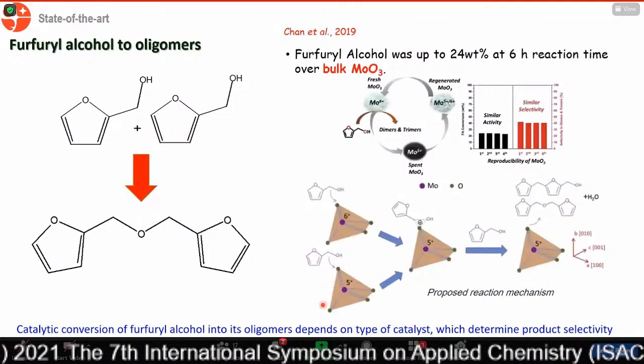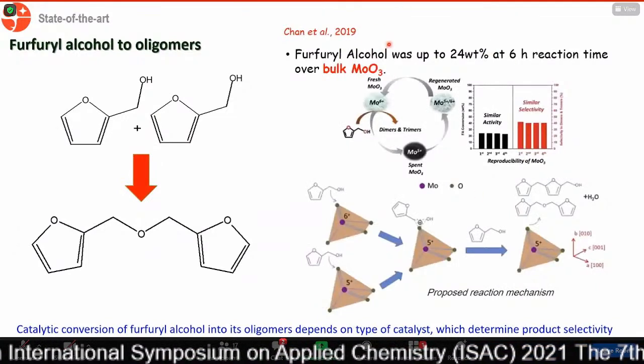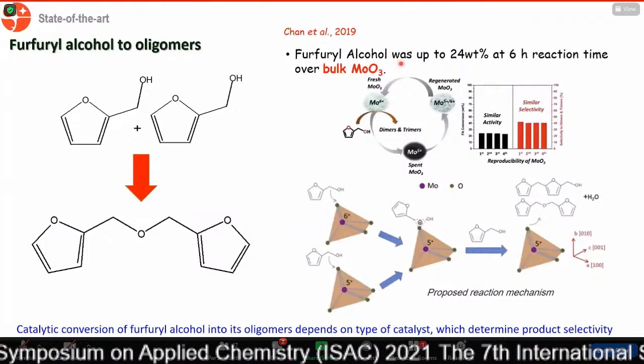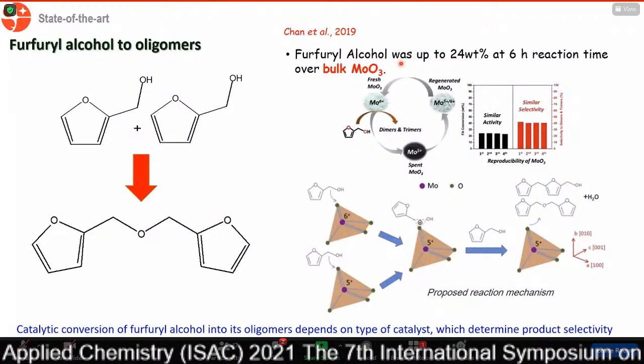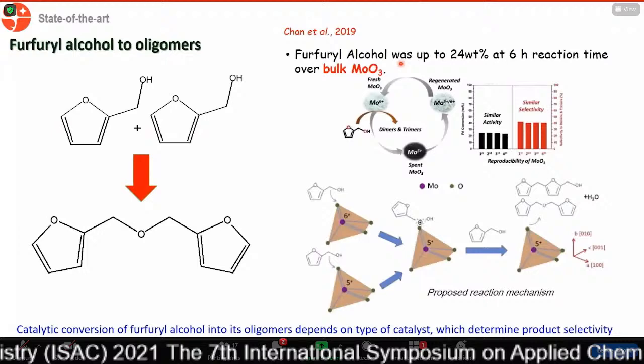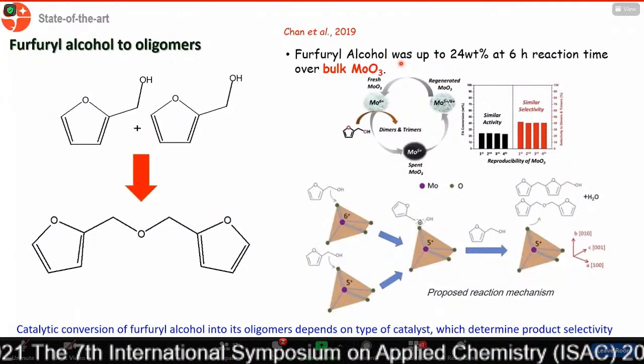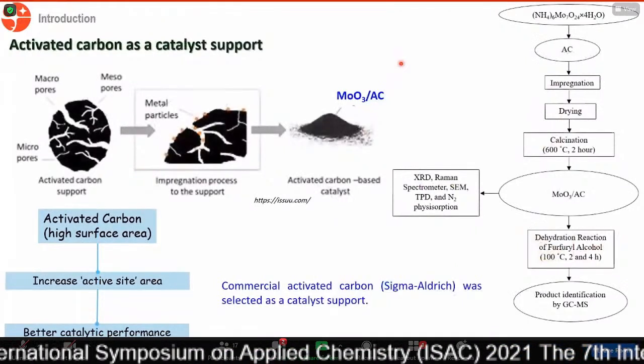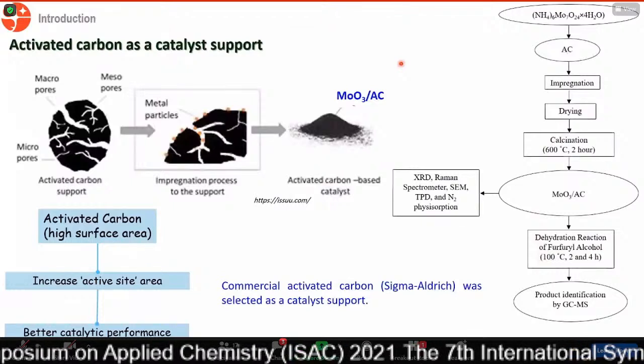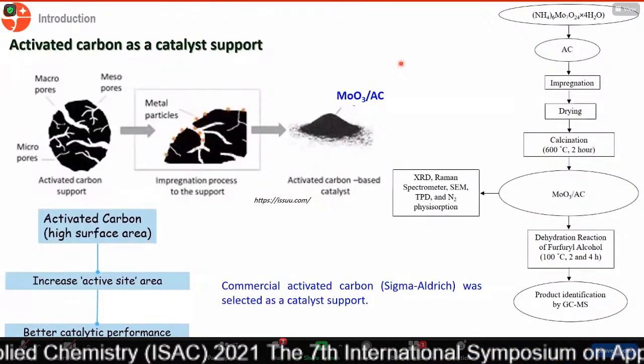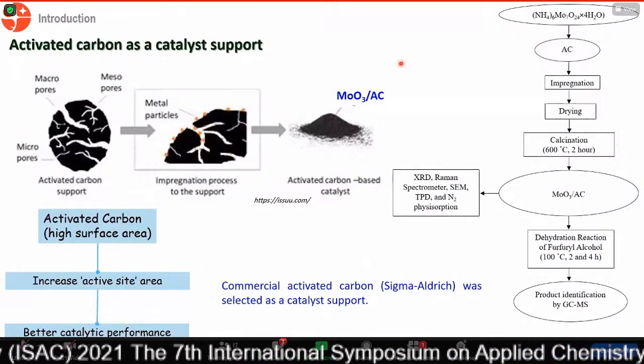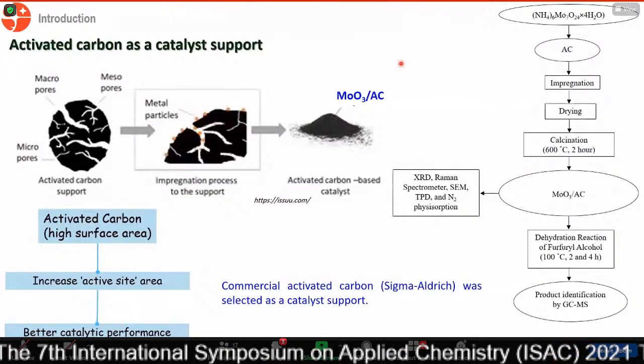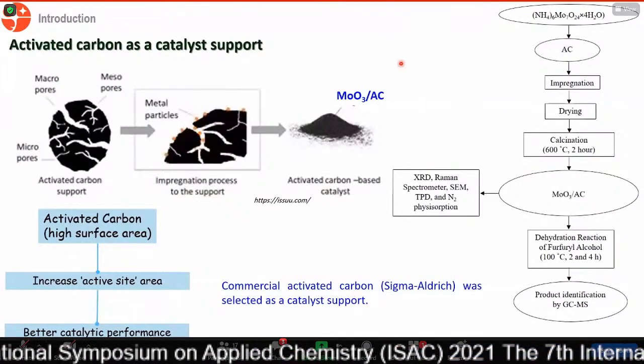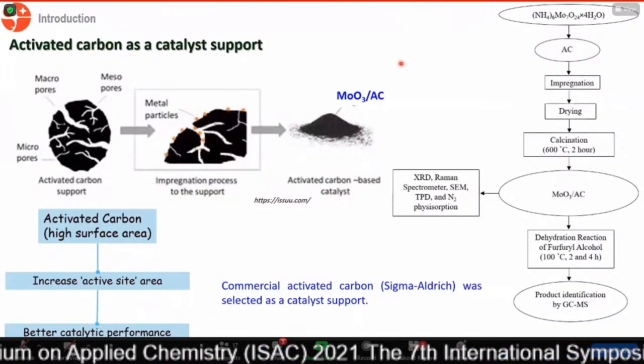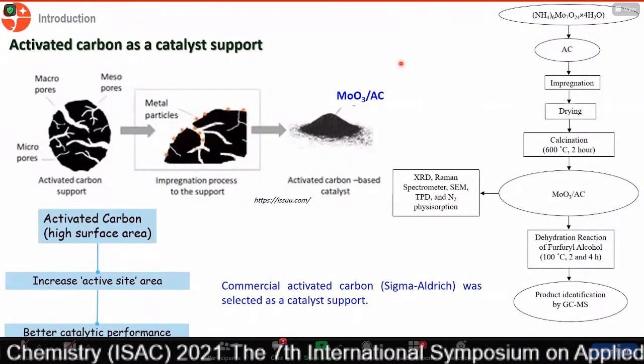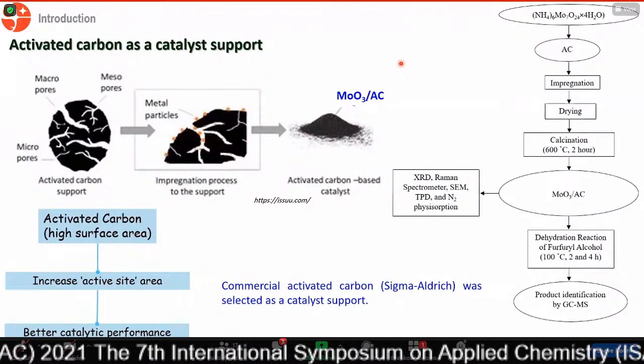Among those catalysts, molybdenum oxide has been reported as an efficient catalyst to convert furfuryl alcohol into its oligomer. This molybdenum oxide has the oxidation number of 6+ and 5+, which is very active for dehydration reaction and condensation of furfuryl alcohol. However, the previous molybdenum oxide was utilized in the bulk form. So our study here is trying to use activated carbon as a support for the molybdenum oxide for this reaction. We select the activated carbon as a support since it has a very high surface area and also very good acidic property, which is very useful for the reaction.